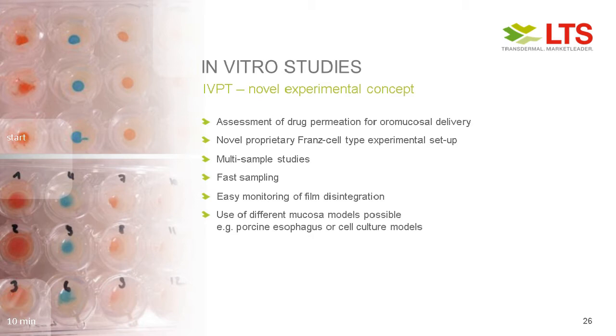So on the left side, you can see a picture starting at the top left, where you see small OTF samples with dyes, colors. So we can see the disintegration coming up. On the bottom left, after 10 minutes, you can see the different formulations, how they have been disintegrating within a small amount of saliva over time. So we can easily monitor visually what is actually happening. For this kind of experiment, we're using different mucosa models. Mostly used is the porcine esophagus model, because simply there's more area than the porcine cheek. Or we have cell culture models, which can be used depending on the API and its properties.